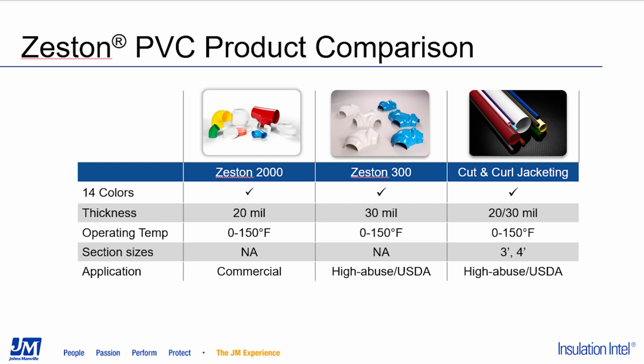You can see the difference between the Zeston 2000 and 300 fittings is the thickness or millage, with the 2000 being a 20 mil product and the 300 being a 30 mil. The cut and curl jacketing is available in both thickness options, 20 or 30 mil. All are rated for an operating temperature range of 0 to 150 degrees Fahrenheit, but you have to remember that this is typically being installed over your insulation system, so it can be applicable to systems operating at temperatures higher than that. A lot of different section sizes available for the fittings.